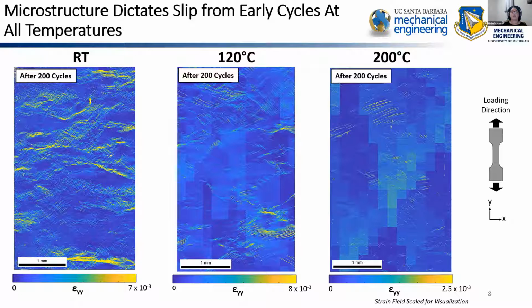You're going to have a more homogeneous yield of the entire material, because you're going to have a reduction in anisotropy. That is why you have significantly less strain overall, or less slip activity, but it's the same mechanism, the same reasons. You still have basal slip first, you're just not seeing it as much because you have significantly lower yield, which means that you're loading it to a significantly smaller portion of its yield for the entire material.